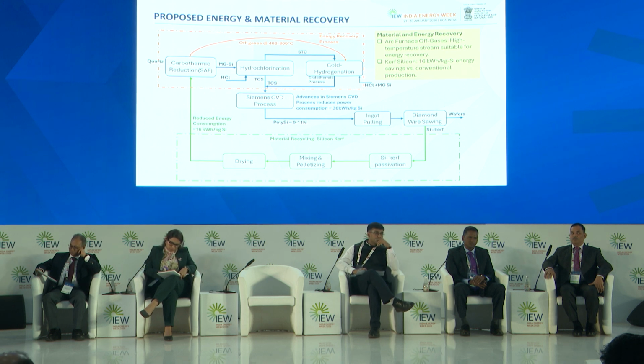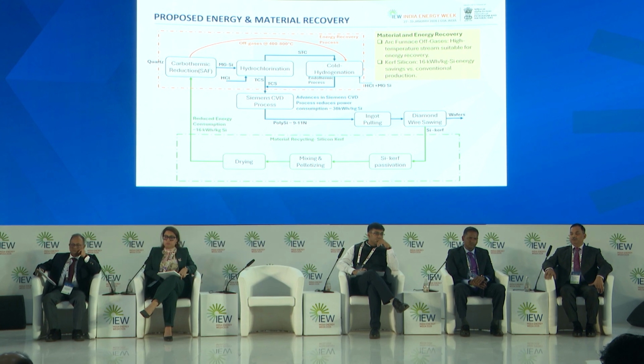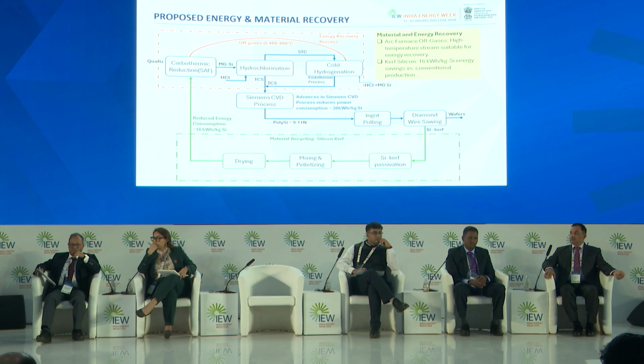Once we get this trichlorosilane, it undergoes the Siemens chemical vapor deposition process, which is a bell jar kind of reactor, which requires a huge amount of electricity and is highly energy intensive. In this process, the polysilicon which is deposited has a purity of 9 to 11 N. Later on, we move on to the ingot pulling process. Afterwards, we slice this ingot into wafers.